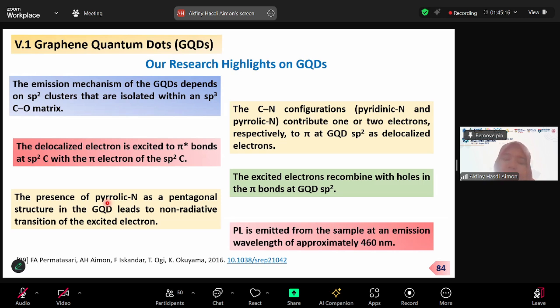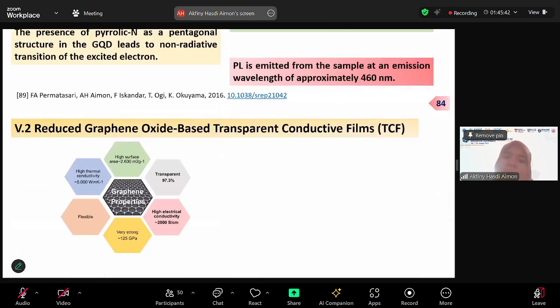And then the presence of pyrrolic N as a pentagonal structure in graphene quantum dot leads to non-radiative transition of the excited electron. And then the excited electrons recombine with holes in the pi bonds at graphene quantum dot sp2. PL is emitted from the sample at an emission wavelength of approximately 460 nanometers.